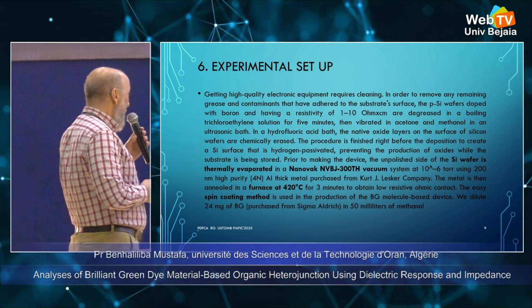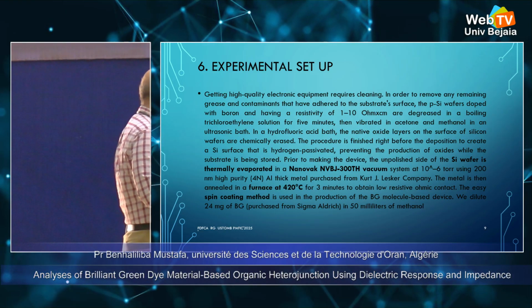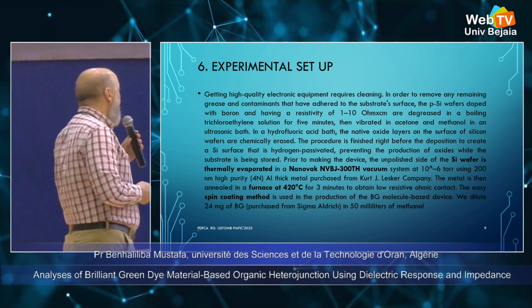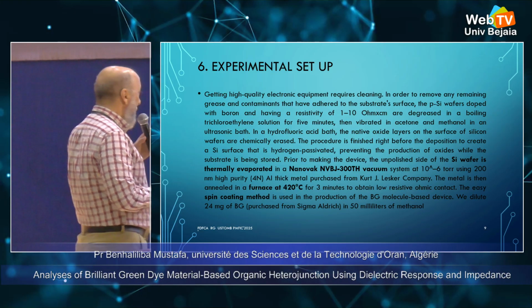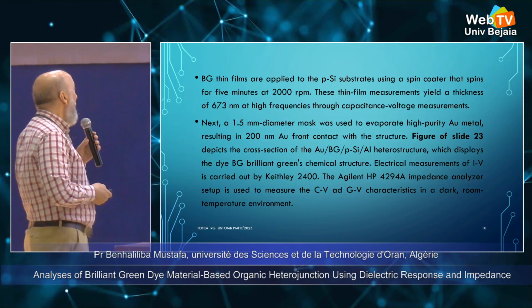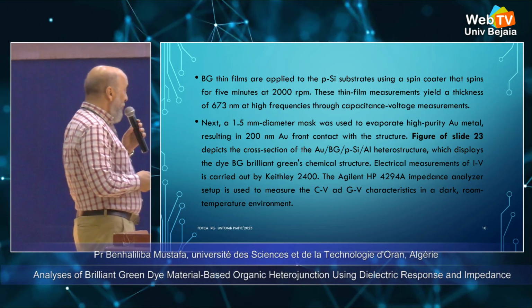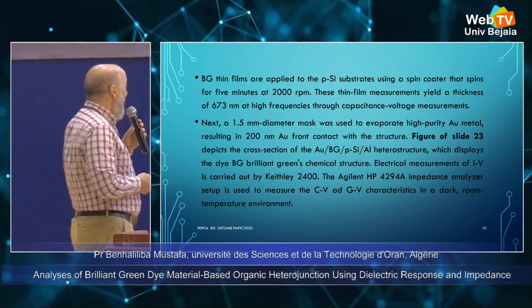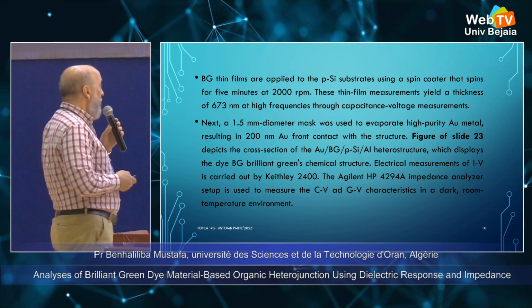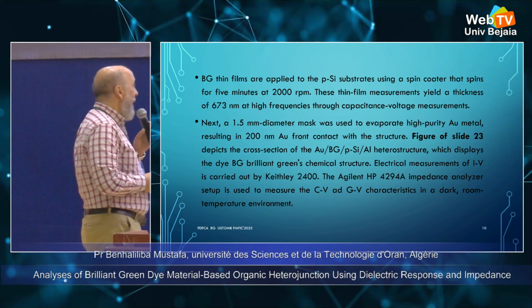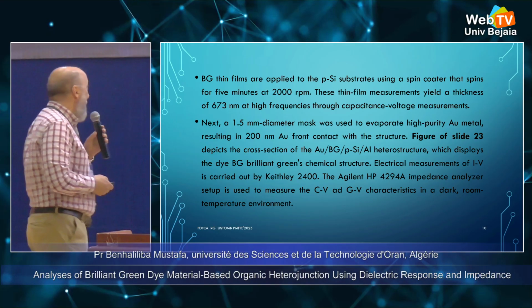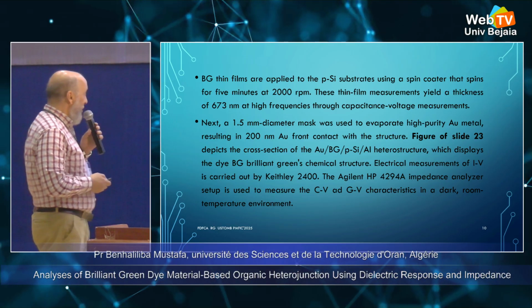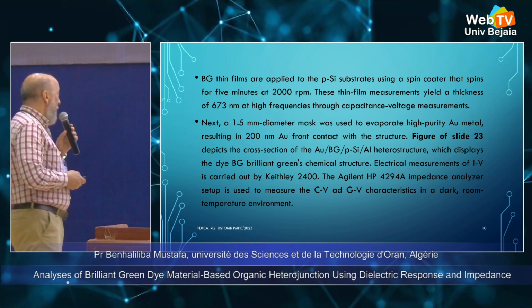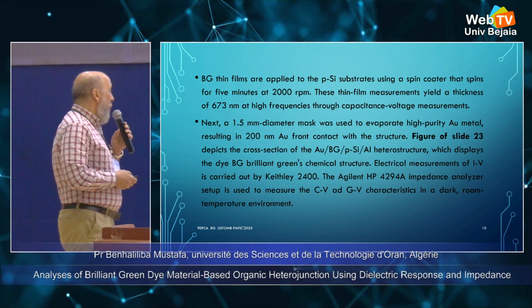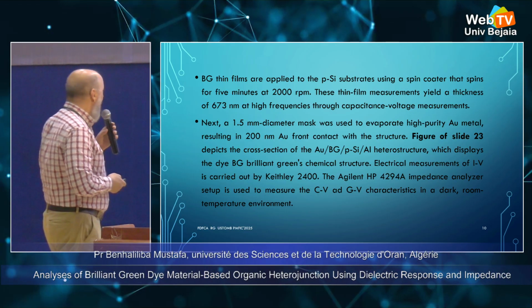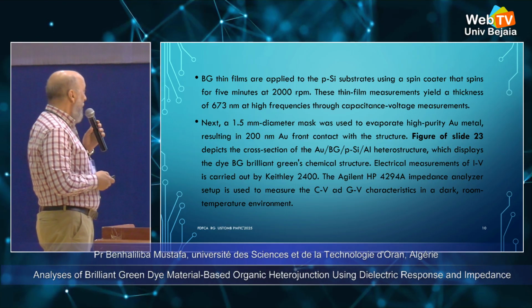The easy spin coating method is used in the production of the BG molecule-based device. We dilute 24 milligram of BG purchased from Sigma-Aldrich in 50 milliliters of methanol. BG thin films are applied to the P-silicon substrate using a spin coater, then spun for 5 minutes at 2000 RPM. This thin film measurement yields a thickness of 673 nanometer at high frequency through capacitance voltage measurement.